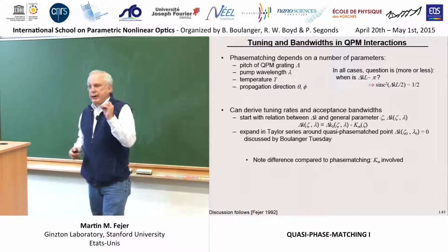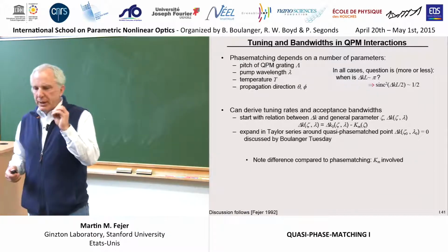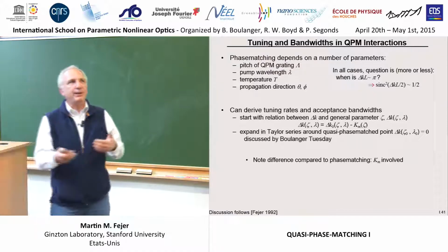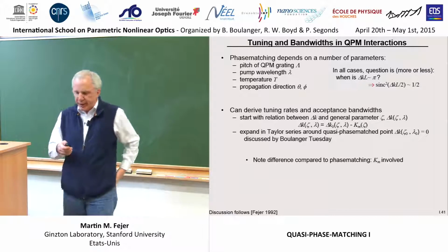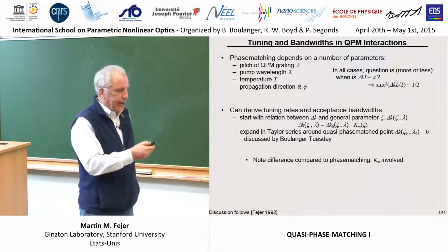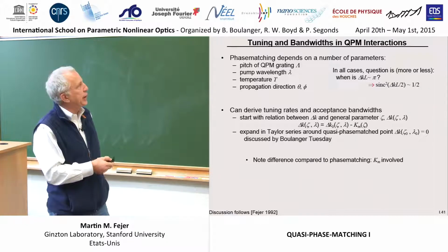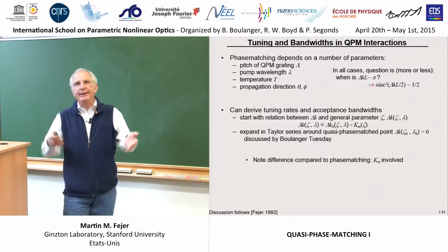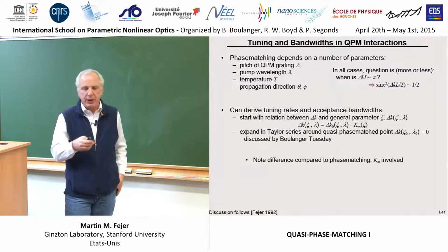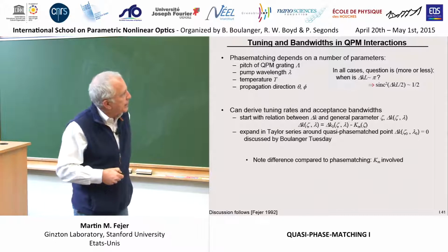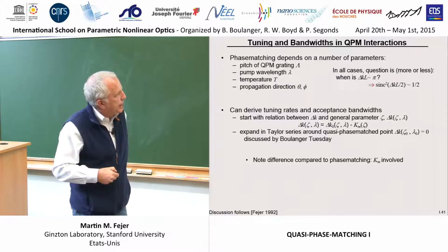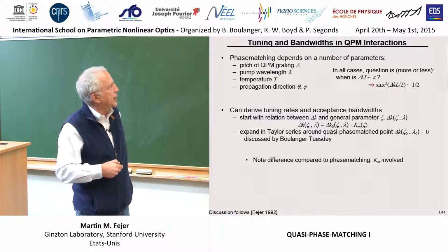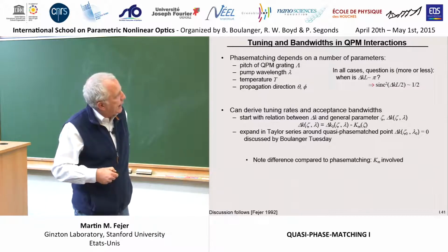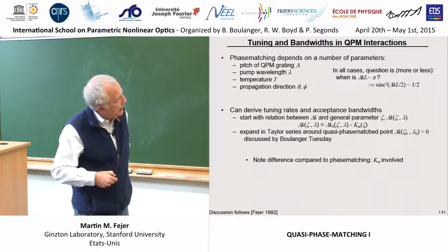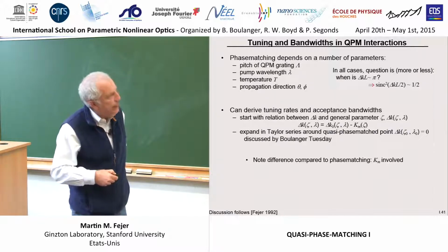Okay, Benoit talked in some length about the acceptance bandwidths and tuning rates for nonlinear processes depending on temperature or angle or whatever variable you happen to be controlling. And one can do the same calculations for quasi-phase matched interactions. I won't walk you through all of that. The concepts are identical to the ones that Benoit talked about. The only difference is, if you remember, he looked at how delta K depended on some parameter zeta, where zeta might be temperature or angle or whatever. And that just depended, in his case, on the material dispersion. If you're quasi-phase matching, the delta K that enters into the problem, remember, you subtracted off a grating K vector.